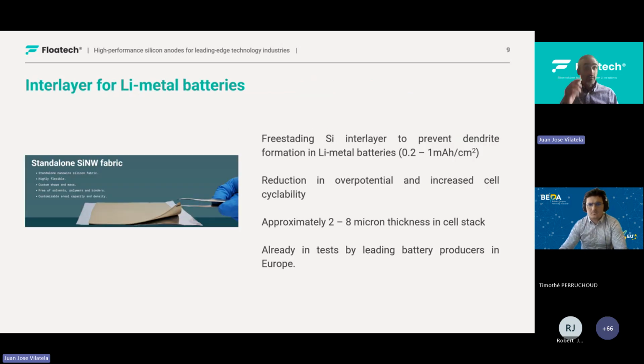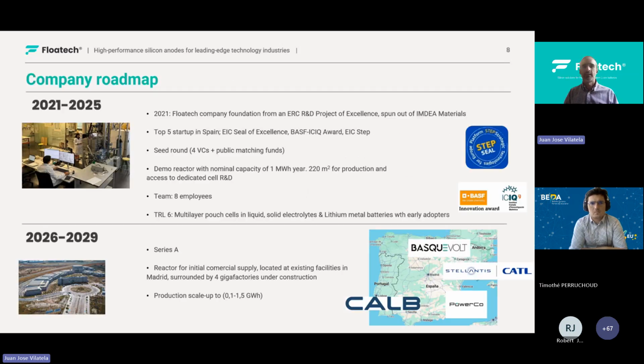If you are a lithium metal battery company, our product is a very thin layer. This goes between the metal foil and the electrolyte. And what it does is it lowers the overpotential for plating and stripping and increases cell cyclability through this lithophilic interlayer. We can make them very thin, typically 8 microns, but we have a target of going down to 2 microns in thickness, and this is already being tested by established battery producers in Europe and elsewhere.